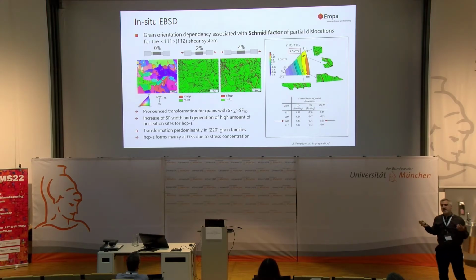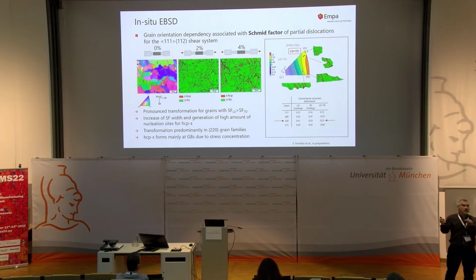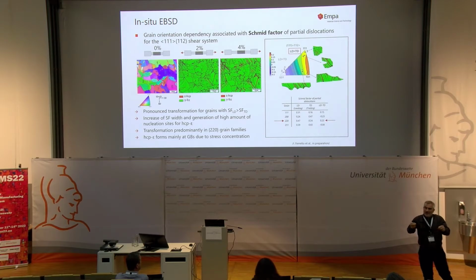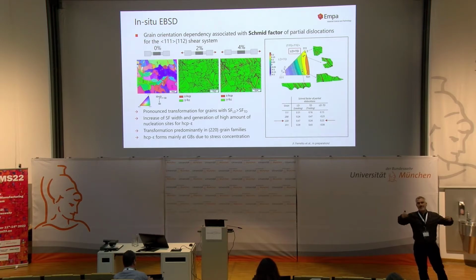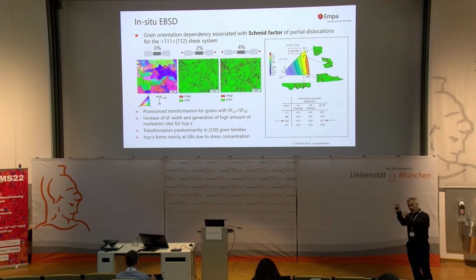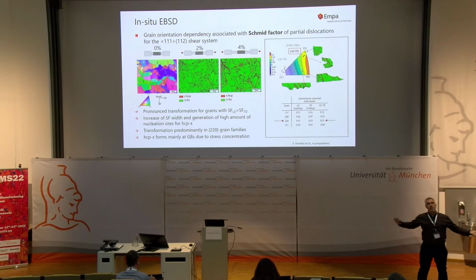And if we apply a stress on there, we see the transformation there. Now what's happening if we apply the stress, the leading partial is larger, so the stacking faults that are already there become larger, they extend, they extend, they extend. And it's these stacking faults that are the precursors for this epsilon. If we have a lot of these stacking faults, and in our AM material we have more than in conventional material, if we have more fulfilling this criterion, then we will have more transformation, and that explains why we do have these orientational differences in our material.